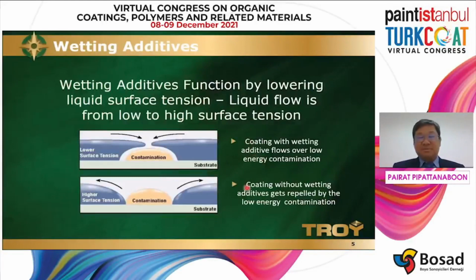The concept of substrate wetting is a picture that you see every day, like this picture here: contamination like oil or silicone oil on the surface of the substrate that you need to coat. If your coating has higher surface tension than the contamination, this is what you see, that you get some crawling. The coating cannot cover the surface. And that's why substrate wetting helps to reduce or lower the surface tension of your coating, so that you are able to coat over the contamination or contaminants.